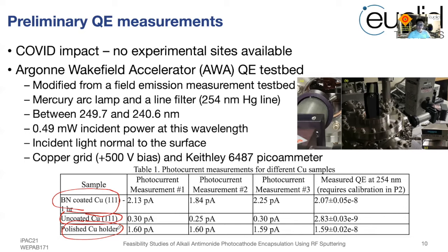I should remind everybody that copper 111, from the literature, has a higher work function compared to other lattice structures or amorphous copper. That's why you can see that from a polished copper holder, which was basically machined from oxygen-free copper, the photocurrent was much higher than for the single lattice wafer. So this is a very promising result, that the hexagonal boron nitride has even increased the QE for a single lattice copper substrate.